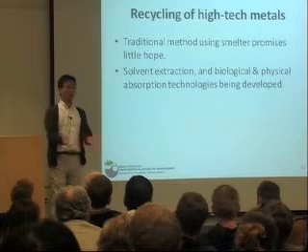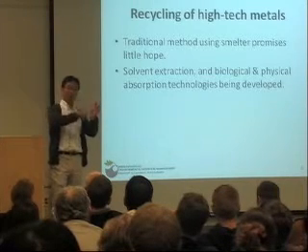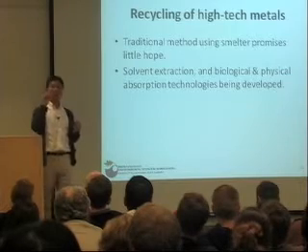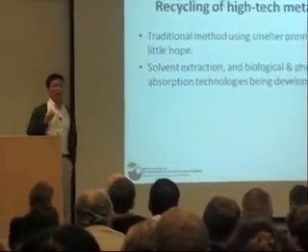If you scrape those surfaces out, they have a fairly high concentration of platinum. But you cannot put those into the smelters because the efficiency and the yield is too low. So some British scientists developed a bacteria that will selectively absorb the platinum, and you can separate the platinum from those bacteria. So there are interesting developments going on for the absorption technologies, not much from the thermal extraction side.